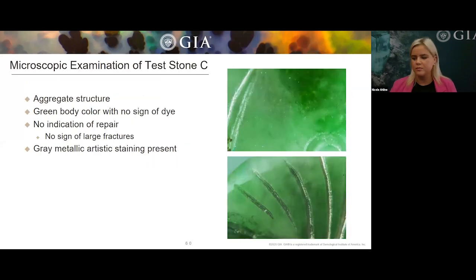So our gemologists are noting when they look at the stone that the stone does have an aggregate structure, aligning with that polariscope. It does have green body color with no signs of dye, which is great because we got those chrome bands in our handheld spectroscope. There's no indication of repair for this carving.